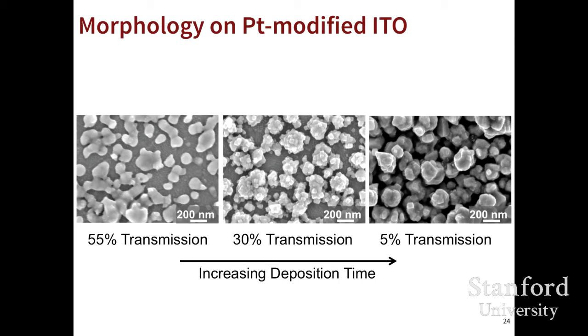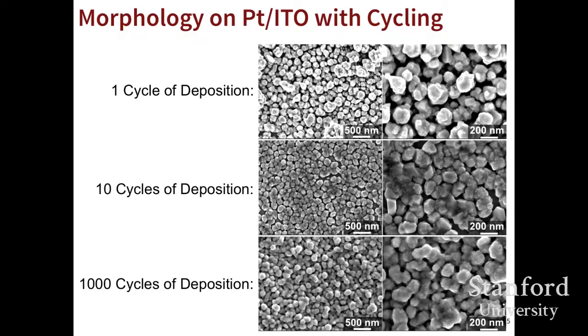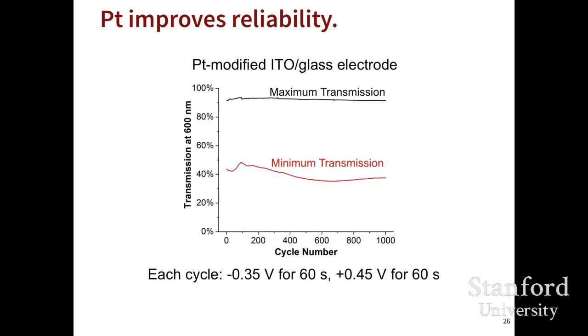We don't have a continuous thin film of metal. We're still getting nanoparticles of metal, but you can see in these SEM images that there's a pretty good distribution. All patches on the window have a fairly similar morphology. And we found that when we cycled it 1,000 times, we didn't get significant changes in the morphology. We believe that in the strip cycle, all of the metal comes off, and we're then starting over again with a clean platinum surface. And with that, when we cycled it back and forth, we got consistent results over 1,000 cycles, and I'll show even more cycles later on in this presentation.